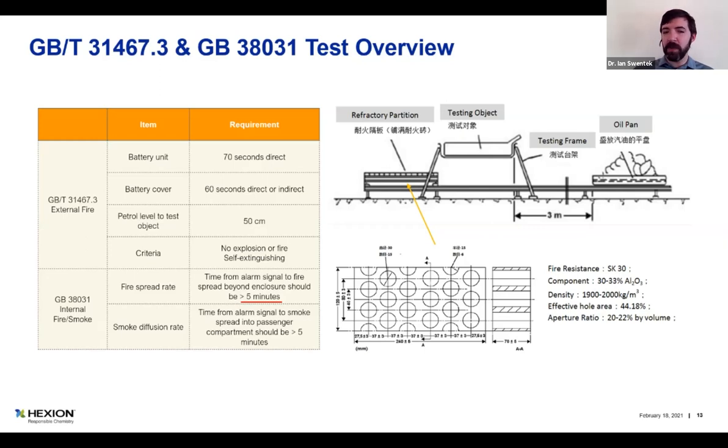And whatever happens at that point, either it has to withstand a cascade failure of the battery pack, or it has to withstand high temperature conditions, or perhaps a combination with mechanically ablative conditions. And that is where the internal temperatures can really climb quite quickly. So the typical test condition for that is a long duration test looking at 1400 Celsius type fire exposure, thermal exposure, and ensuring that the battery enclosure itself will protect against that.